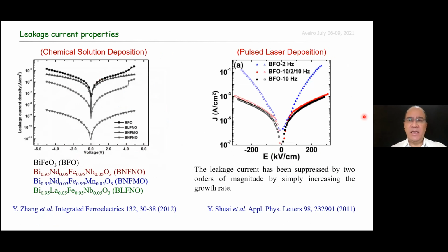So the leakage current does not depend on the deposition method. It is observed in BFO thin films prepared from chemical or physical routes. However, the leakage current can be changed by introducing some kind of dopant atom, as observed in this left figure, or tuning some specific parameter during the synthesis, as shown in this figure on the right. It is important to note that in the right case, the leakage current has been suppressed by 2 orders of magnitude, increasing the growth rate.